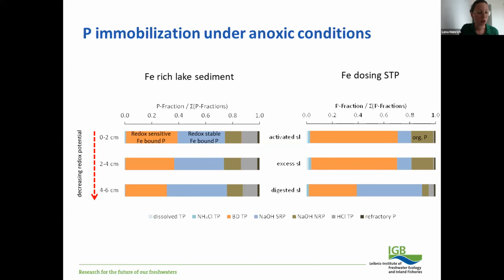And we see the orange bars decrease and the blue bars increase with decreasing redox potential in both systems. And this indicates an immobilization of the iron-bound phosphorus regarding anoxic conditions. In addition to the sequential extraction, we studied these two systems by microscopy, XRD, and XRD quantifications. And these methods demonstrate that the redox stable phosphorus binding form bound to iron is related to the ferrous iron phosphorus mineral Vivianite.